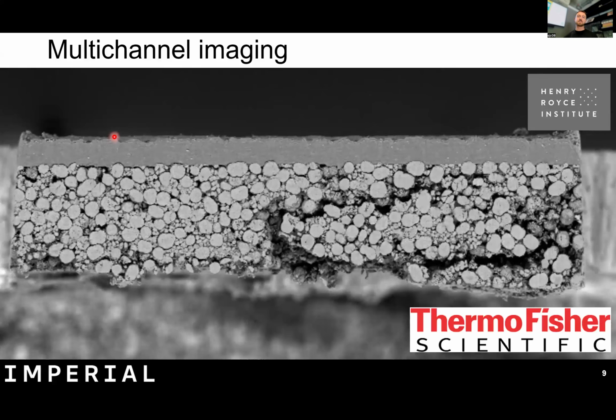So here's our nice image of a cathode again, and I can overlay the deep learning based vision transformer featurization stack on top. Again, it's just PC 1, 2, and 3 stuck on top. Then I can pass those to a classifier and use those to get a really high quality segmentation of the image. And again, with an anode of graphite and silicon in it, I can generate some really high quality segmentations there as well.